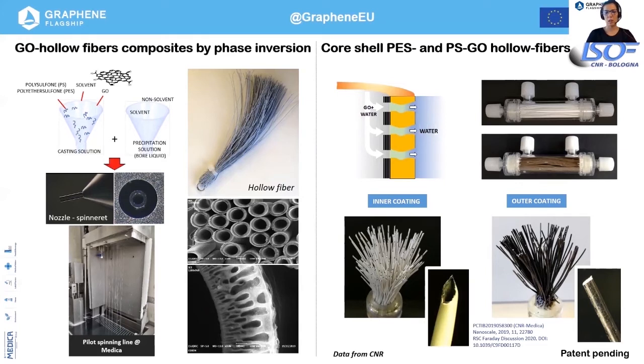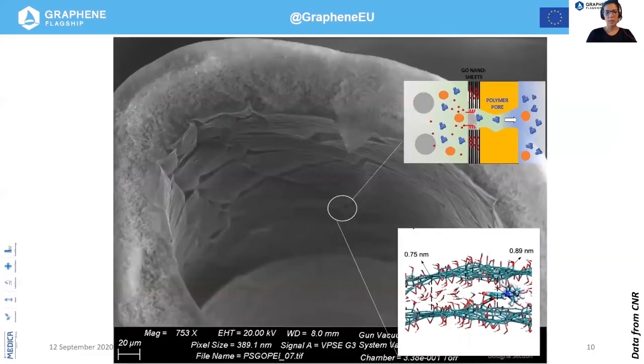This process is absolutely stable, as demonstrated by the filtration of hundreds of liters of water without the release of graphene oxide. This is an SEM image of a polyether sulfone hollow fiber with an inner coating of chemically modified graphene oxide. This coating looks pretty homogeneous, and by XRD it has been demonstrated that it consists of 10 nanosheets of GO overlapping.